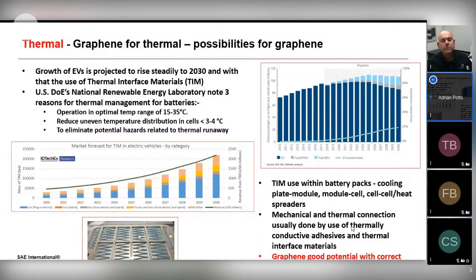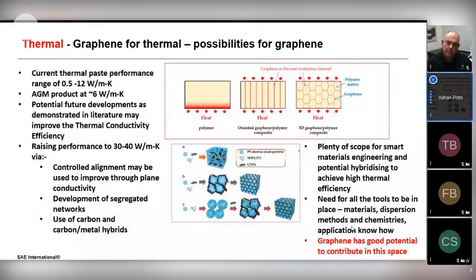NREL put out their guidance on the need for control of battery temperature, which we see there top left, and clearly there's an opportunity for graphene to be used well in those types of application, again with the correct dispersion and the correct particle formatting. If we look at the current market and range of materials performance for those types of applications, we sit sort of in the middle of current thermal paste adhesive product offerings, at around 6 watts per meter K. Typical products out there are around 0.5 to 12. We believe there's great performance advantages to be gained in materials engineering and materials engineered solutions.